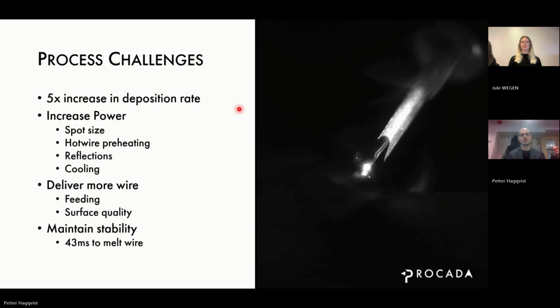When we increase the overall laser power, there will also be reflections, because maybe 40% of the laser power actually goes into the material. The rest will be reflected. And that needs to be taken care of, because we have sensitive materials, sensitive equipment in the chamber. And if you were to point a 5 kilowatt laser beam at that equipment, unless it's properly cooled and reflective itself, it will burn. So there was a lot of engineering effort spent into cooling stuff and shielding stuff.